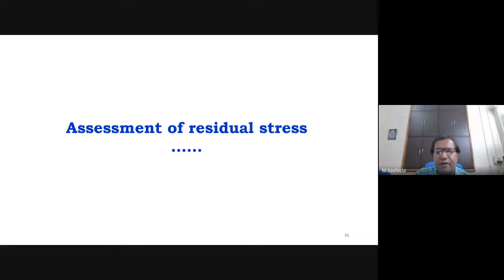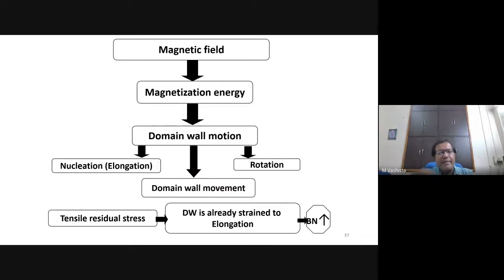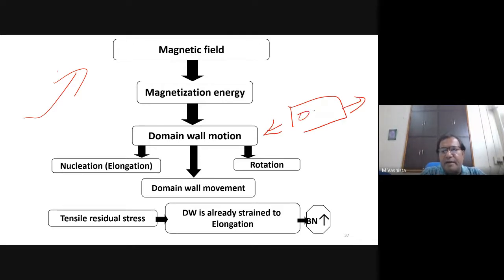How will it be used for assessment of residual stress? Same block diagram I am considering, but I told you that if the material has tensile residual stress, porosity will increase, cracks will increase, voids will increase. But remember, this tensile residual stress will not be biased. It will not differentiate that I have to elongate the void and only elongate the porosity. It will elongate each and everything. Each and everything means it will also elongate the domain wall. If domain wall is present inside the material, domain wall will also be stressed or elongated by tensile residual stress.